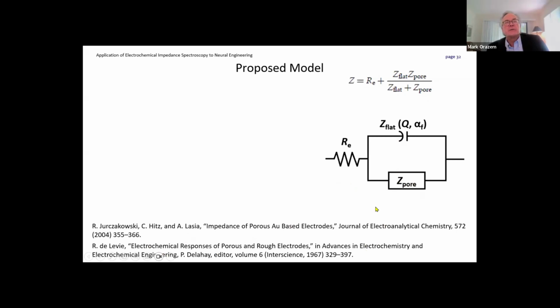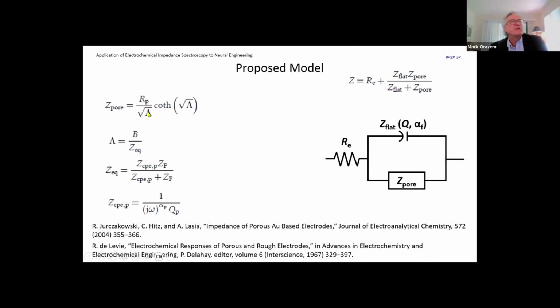So this equation here represents this impedance. Now let's take a look at what each of these terms are. For the pore, we have a pore resistance divided by the square root of lambda, we'll worry about lambda in a second, times the hyperbolic cotangent of the square root of lambda. Lambda is a constant divided by an equivalent impedance, and this impedance is the impedance on the pore wall. This equivalent impedance is the parallel combination of a constant phase element shown here and a Faradaic contribution. And this Faradaic contribution, which I'm showing you here as a series of a resistance and a capacitance, is really due to the iridium oxidation and reduction.